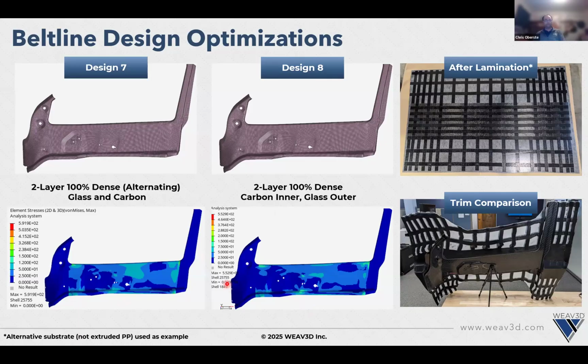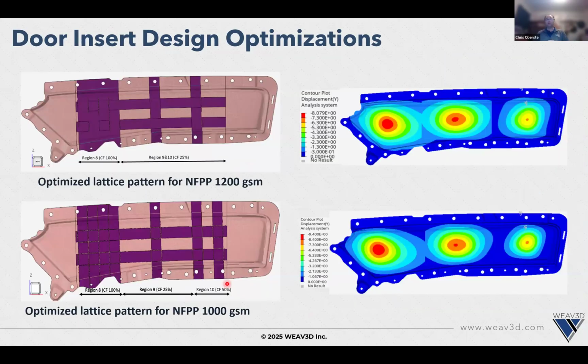On the other side, when we look at the door insert, we have 2 different designs that we came up with. So again, starting with the 1,700 grams per square meter natural fiber nonwoven, we have reduced that to a 1,200 grams per square meter with lattice. So you can see we have a high density region aligned with this high stress point here. And then we have additional tapes adding some extra stiffness as we move away from that.